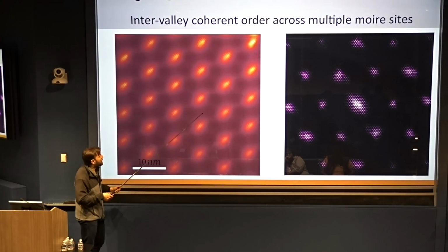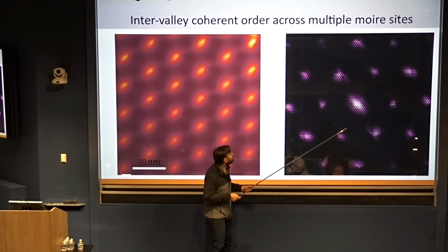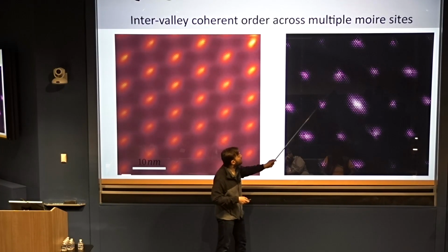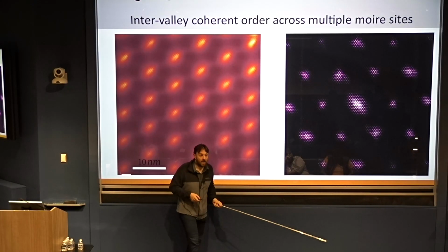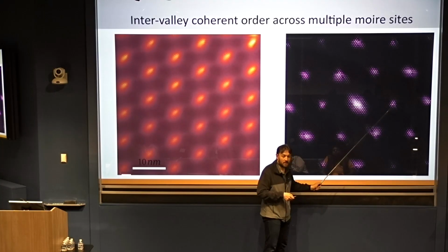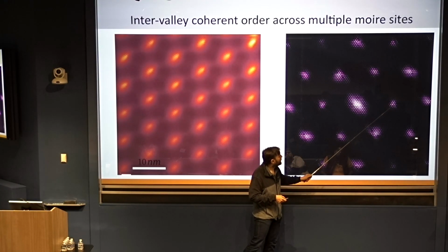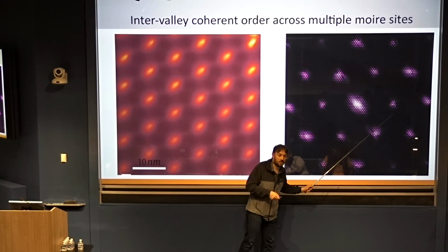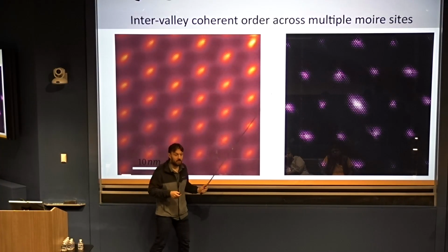And now if you do a Fourier image of this picture, instead of having peaks that would correspond to the graphene lattice and to this kind of reconstruction, you actually get a collection of peaks. Essentially you get more resolution in K-space, and you immediately observe additional periodicity. And this periodicity, between the small dots, actually comes from this Moiré length scale, okay?